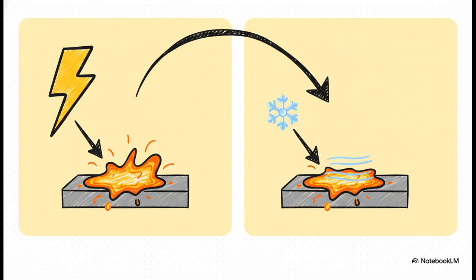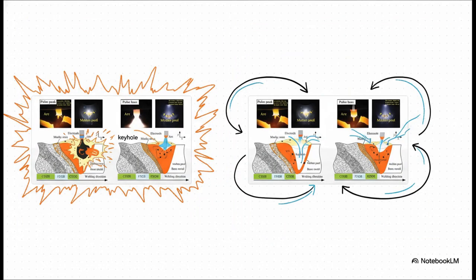You have the peak current, that's the high-energy blast that does the heavy lifting, melting the aluminum and creating the weld pool. But then it immediately drops to a base current, which is just enough energy to keep the arc going, but it allows that molten pool to cool down and start to solidify before the next pulse hits. It's a brilliant rhythm. So you can actually see what's happening physically here. During that peak current, the intense energy literally pushes the molten metal aside, creating what's called a keyhole that gives you deep penetration into the joint.